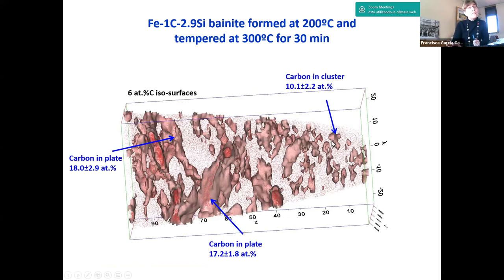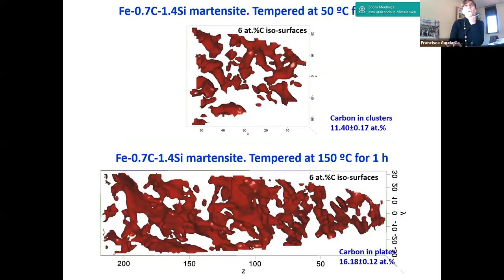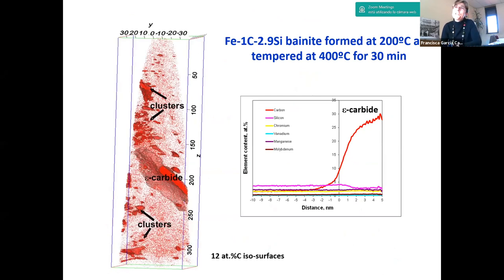You can see the carbon clustering is still there, but we see these well-formed features with higher carbon content that compare quite well with Fe4C. And look, at the top, martensite tempered at 50 degrees C, carbon clusters. At the bottom, martensite tempered at 150 degrees C. You can see the same level of carbon in those features. Eventually, with extra energy, epsilon carbide will form in bainite, as it formed in martensitic structures, quenching and partitioning, and quenched structures at lower temperatures.